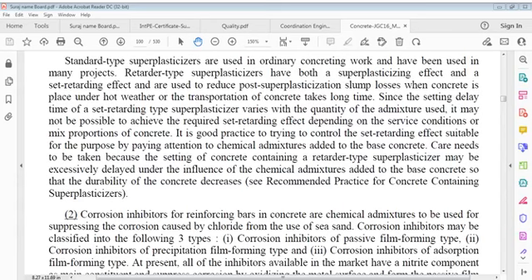Setting delay time of a set retarding type superplasticizer varies with quantity of admixture used. It may not be possible to achieve the required set retarding effect depending on service conditions or mixed proportions of concrete. It's good practice to try to control set retarding time effect suitable for purpose by paying attention to chemical admixtures added to base concrete. Care needs to be taken because the setting of concrete containing a retarder-type superplasticizer may be excessively delayed under influence of chemical admixture added to base concrete, so the durability of concrete decreases.